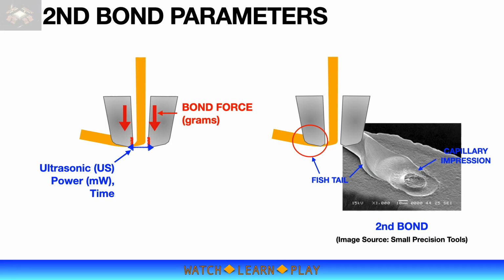If too much bond force is applied on the second bond, the stitch will be smaller and the capillary impression is deeper or shattered. In some cases, this will also result in a lifted stitch problem because the fishtail that is left on the lead is too small. Or if the stitch is not lifting, the tail end formation after the second bond will be inconsistent and will cause a frequent or occasional EFO error when forming the free air ball. A poor second bond will also result in low pull test results.